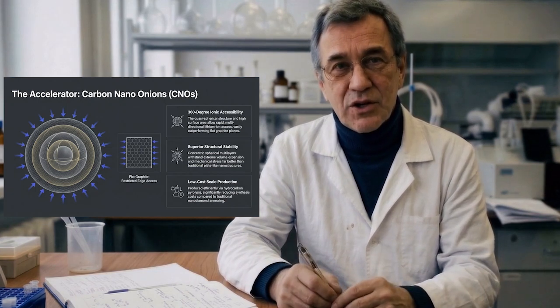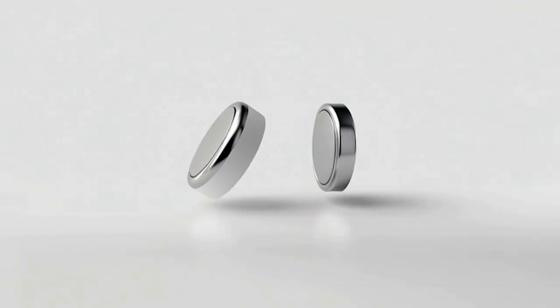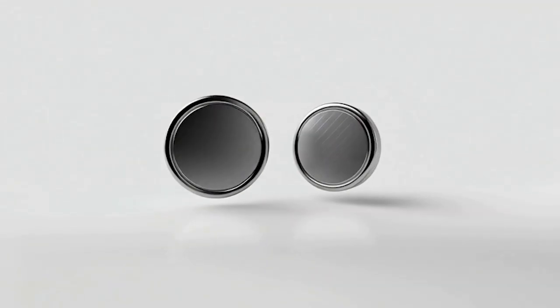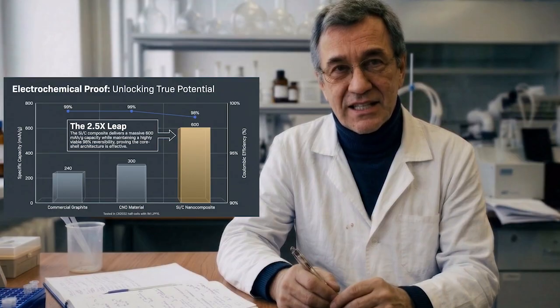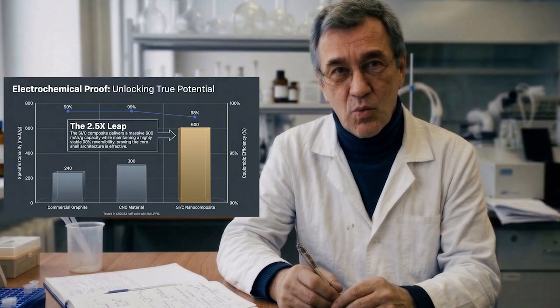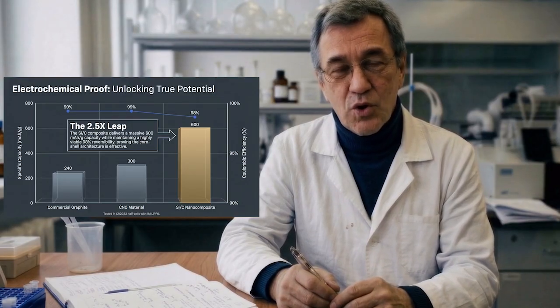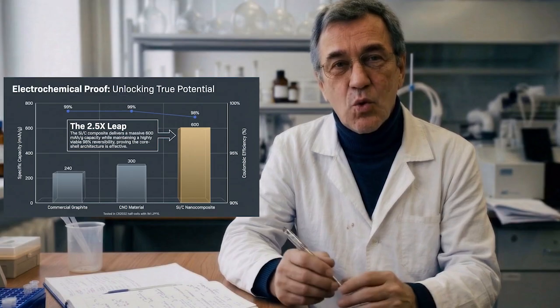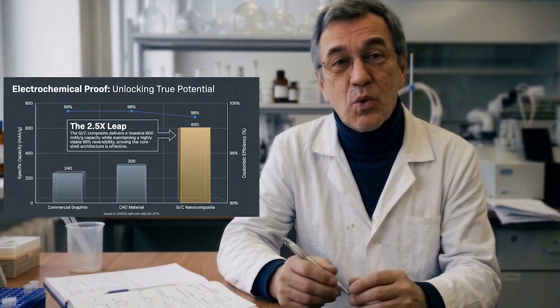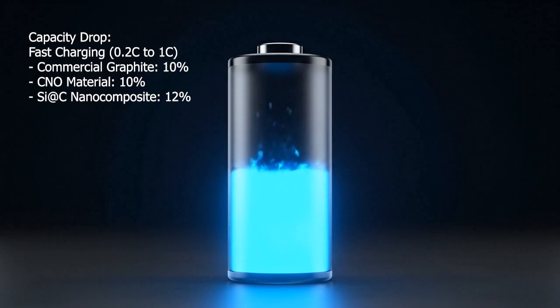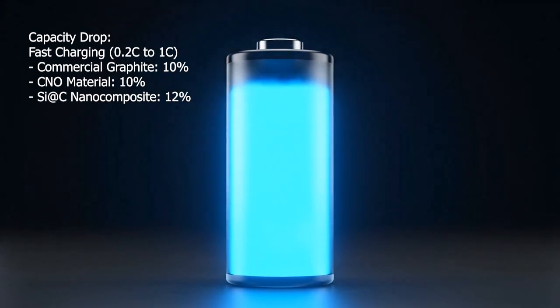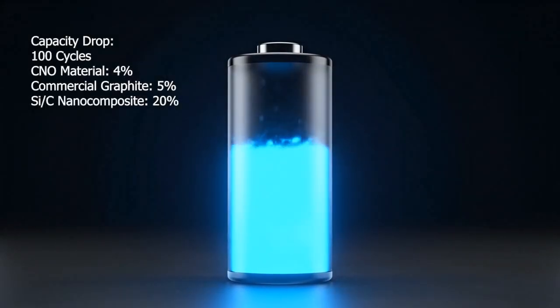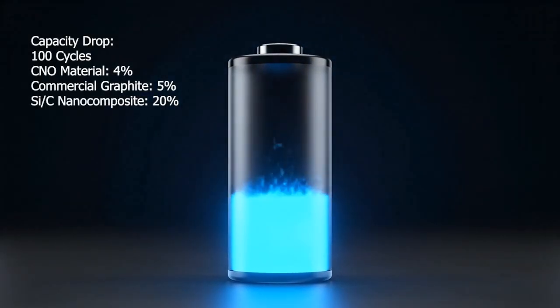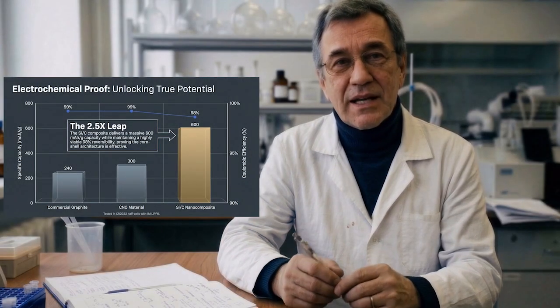The true test of any material is in its performance. To evaluate our silicon, carbon, and CNO materials, we assembled them into standard CR2032 coin cells. These were tested against a lithium metal electrode. We developed a rigorous three-stage testing protocol. First, we cycled the cells at a low, slow current to determine their maximum reversible capacity. Next, we tested the materials at different charge and discharge rates. This tells us how well the battery performs under demanding conditions like fast charging. Finally, we subjected the cells to 100 cycles. This is the ultimate test of durability, measuring how much capacity is lost over the lifetime of the electrode.